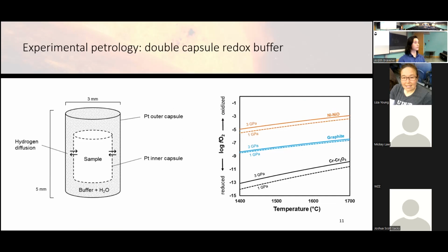And in fact, that large scale experiment is exactly what we need for investigating redox, because the way that we experimentally constrain oxygen fugacity, hydrogen fugacity, and redox state within these experiments is using this double capsule technique, where you can see within the very center of that capsule, we have our sample. And that's all enclosed in a little platinum container that's supposedly inert to other reactions. And then directly outside the sample, we have our redox buffer, which is our metal-metal oxide pairing that sets the oxygen fugacity. And again, all of that's enclosed in an outer platinum capsule.